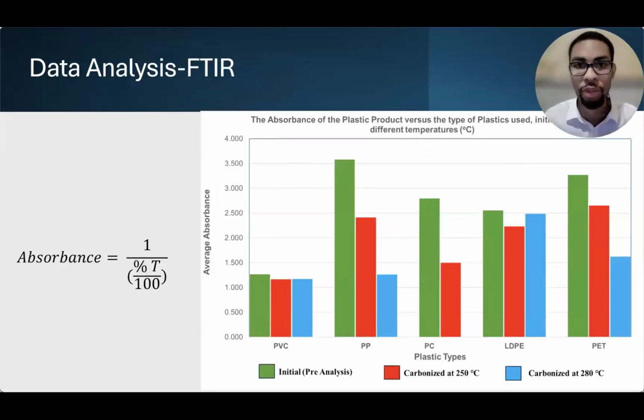Now, the usage of FTIR was essential to determine how temperature affected the breakdown of our plastic samples. This was given as a function of absorbance that was determined from the FTIR spectra that was completed for each plastic sample. A decrease in absorbance would indicate a greater decomposition of those samples. And this trend was observed for the majority of the plastic samples, as we do see a decrease in absorbance as we increase the temperature. However, we do see a bit of variability with the LDPE results.